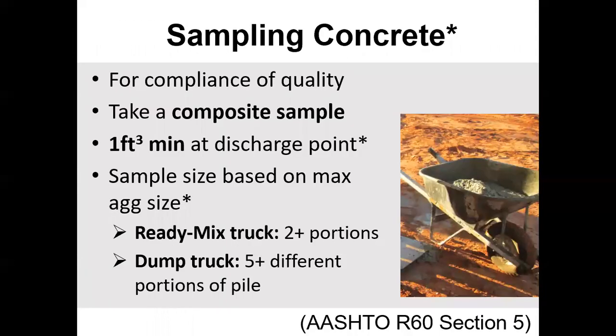Sampling concrete is a composite sample. I've had people say they've been testing concrete for 30 years and never taken a composite sample — just a single sample. Well, congratulations, you've been doing it wrong for 30 years. It is a composite sample, meaning you take multiple portions, multiple increments, combine them together, and mix them into one composite sample. You want at least one cubic foot minimum — especially for strength — though a good wheelbarrow full of about two cubic feet is ideal.